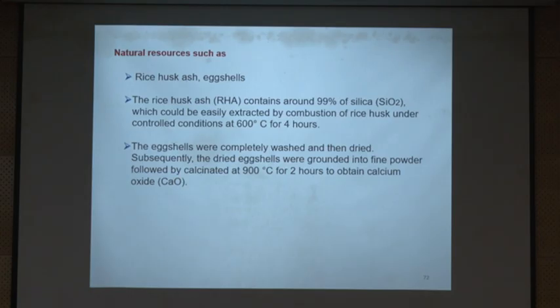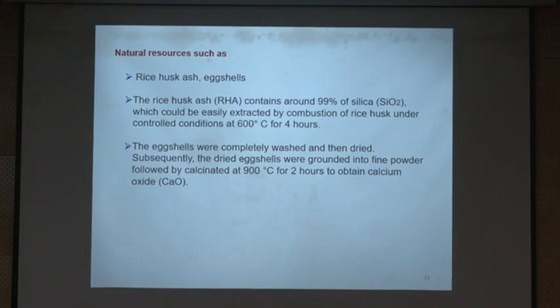If you see here, as I mentioned, rice husk is the major source of silica, right. It contains almost 99% of silica. And then eggshell contains calcium carbonate. If you heat it, make it powder, and heat it, what happens? It dissociates into calcium oxide plus carbon dioxide. So carbon dioxide will evaporate. And then basing upon the selection of this material, 1:1, 1:2, or 1:3, we will get calcium silicate, dicalcium silicate, and tricalcium silicate, right. So selection is also very important.